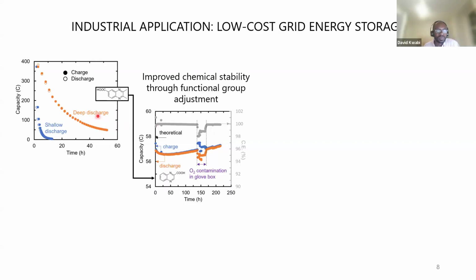Okay, so it's a fairly subtle chemical modification to the structure of the molecule. But we found that making this modification actually ended up boosting our lifetime by a significant fraction. So we're again going from losing most of our capacity in 2 days to not actually being statistically able to measure a rate of capacity fade because it's so slow. We think it's on the order of a couple % a year, extrapolating from some data we gathered over the course of weeks. So again, the takeaway is that we can really get significantly improved chemical stability of these organic molecules through making some subtle but targeted functional group adjustments.